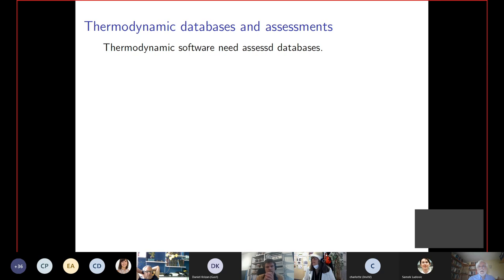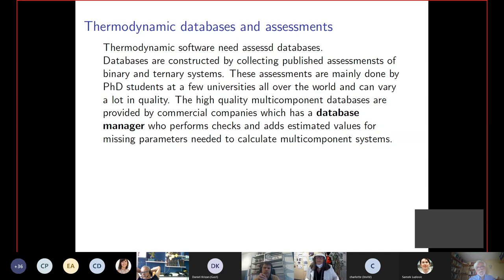I would like to emphasize that software is never better than the database you're working with. All these results depend on how good a database you have. And that is the strength of these commercial companies like Thermocalc or FactSage. They have spent 20 or 30 years developing databases. The problem I found is that they don't like to change models, because if you change a model, you have to reassess the database, and that takes time.